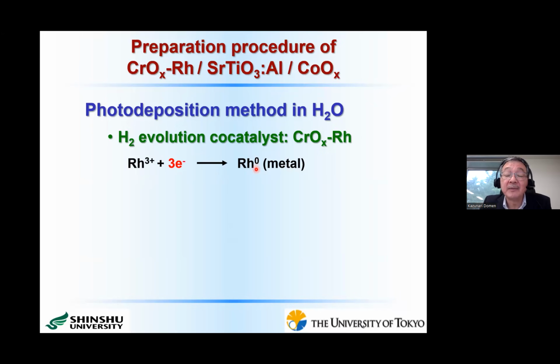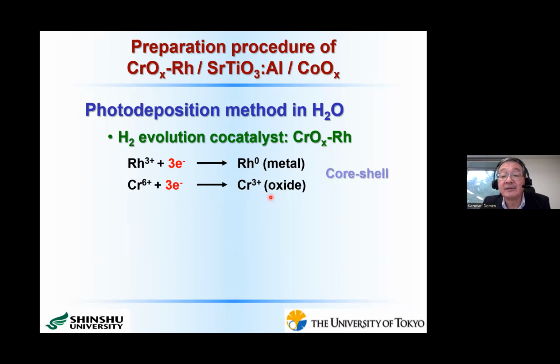But if this rhodium metal nanoparticle is exposed to the surface, then a reverse reaction proceeds. I mean that hydrogen and oxygen form water molecules. So to prevent the reverse reaction, we coat these metallic rhodium nanoparticles with chromium oxide hydroxide. That is a chromium 3+ containing material. In this case, again, we use photoexcited electrons to reduce chromium 6+ into chromium 3+. By these two reactions, we can construct a core-shell structure for hydrogen evolution.